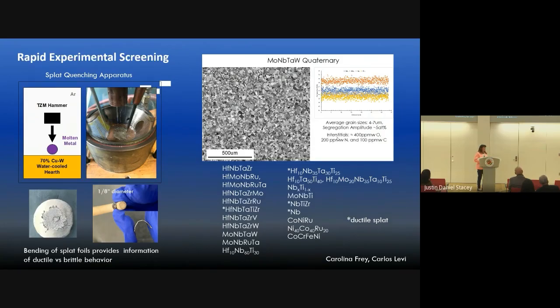about 50 microns thick. So you really have to take a conventional splat quench apparatus and amp it up, both with TZM and copper tungsten, so that we survive these very high temperature materials. So it's not enough material to do much of anything with. You could make some small micro tensile samples. We took some strips out and sent them off to our friends at Johns Hopkins who measured melting temperatures for some of these materials, and things like melting temperatures we don't know. So there's a lot you can do with a little bit of material.